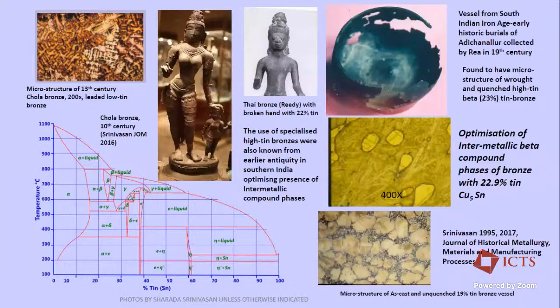And that's quite sensible in a way, because below about 15% tin is the range in which the alpha solid solution of tin in copper forms. And for instance, here you see the microstructure of a Chola bronze. And so you see this very coppery color, because this is low tin bronze, not much tin in it. But please note the color, because that's quite significant. And this dendritic structure, which is also related to the cast process.